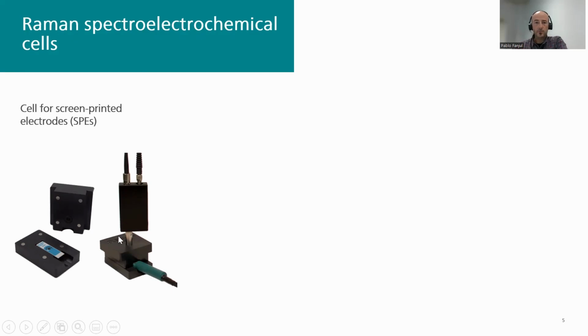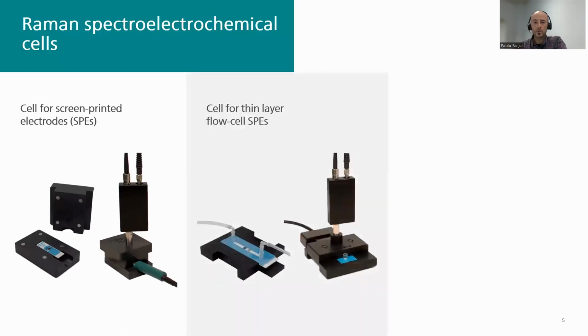And in this configuration, we have the Raman probe just on top of the screen-printed electrode, and we have the solution in between the Raman probe and the electrode. We have here 2 fiber optics. One is coming from the laser for the excitation of the sample, and the other one is going to the spectrometer that collects the Raman signal and sends it to the detector. And then here we have the electrical connections between the electrode and the potentiostat. This is the cell for working with screen-printed electrodes.